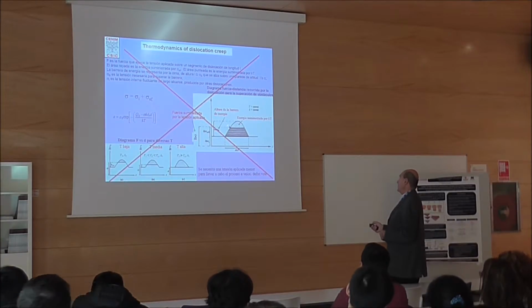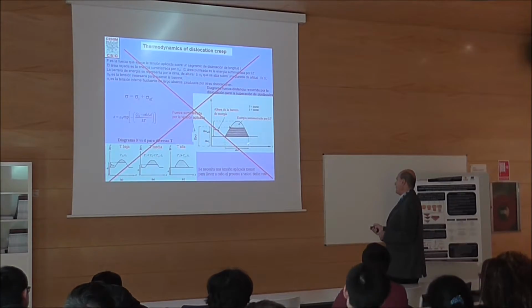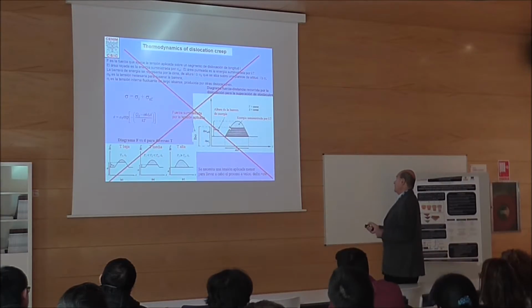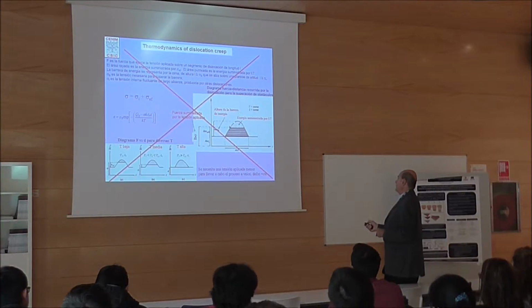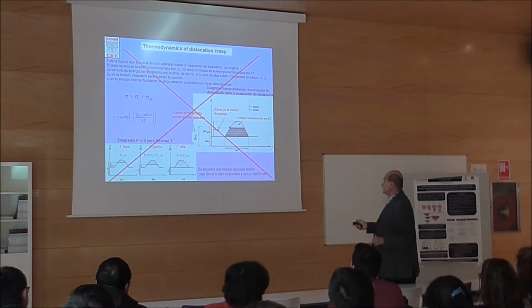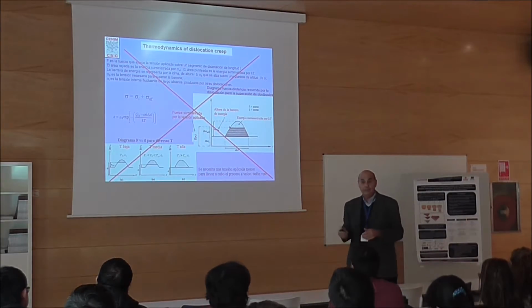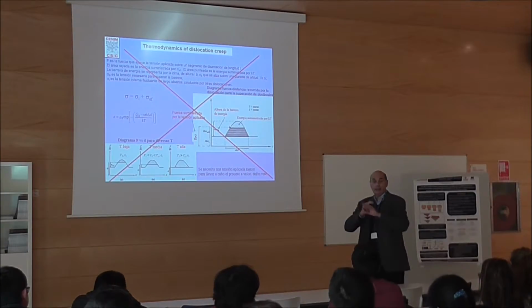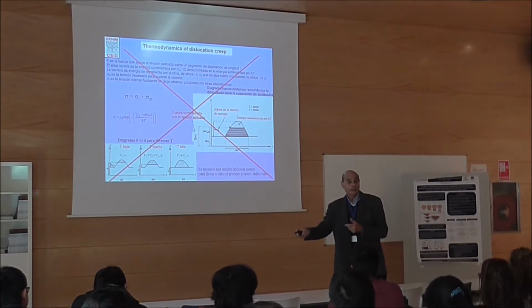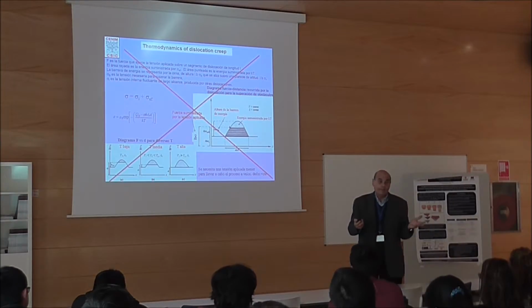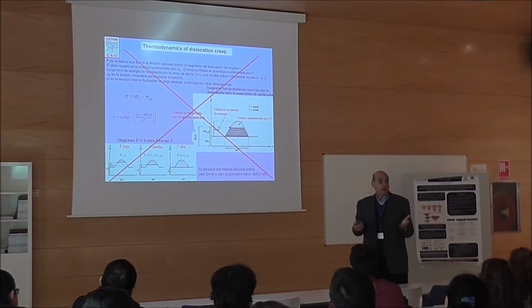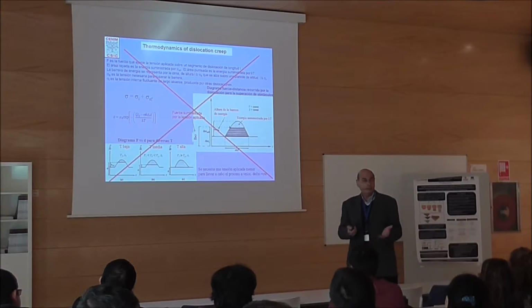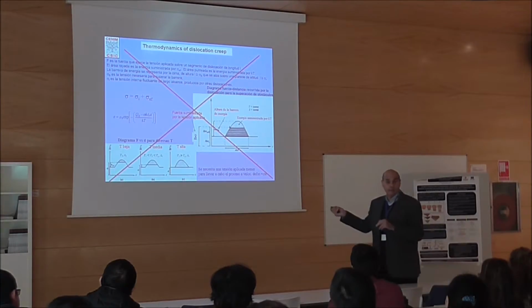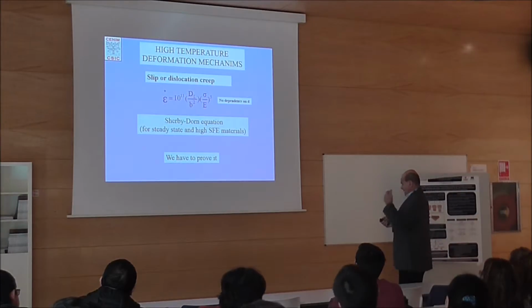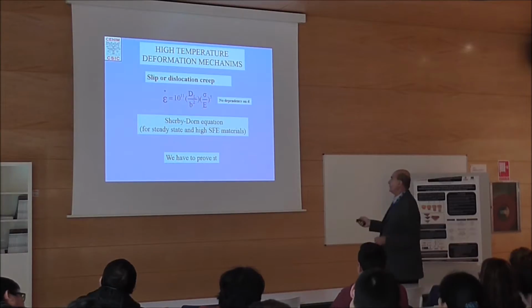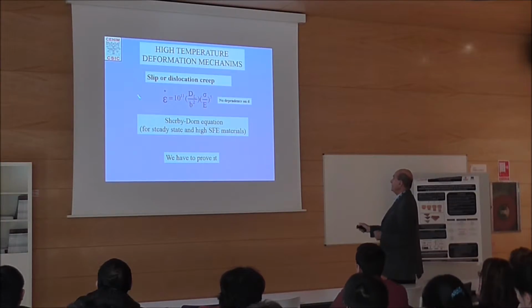Here you press against the obstacle, and this is the energy of the barrier. You press here with my machine, and this is the thermal energy. To overcome the obstacle, you have thermal energy and mechanical energy. And this is an activation volume. The volume is the dislocation overcoming this obstacle, area times Burgers vector, and this is an activation volume. This is a parameter that I think cannot predict anything. It doesn't bring anything. But again, perhaps this is not fair, because many scientists use this. So I put what I believe. It's a matter of belief. This is my view of dislocation creep, the creep constitutive equation.